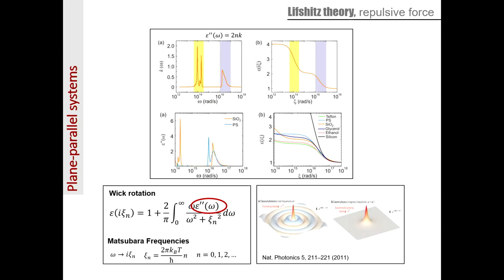I come from a multifunctional optical materials group. We try to modify the optical properties of our materials. And here I'm showing you the absorption coefficient of a bulk silica material, which is related to the losses like this. This is the real part of the refractive index. And then when we do the rotation, anytime we have an absorption band, we get a slope in our curve. And whenever the system is transparent, we have planar bands. So in the end, we need to have a look at plots like these ones where we are characterizing our materials, trying to find that inequation that I told you before.